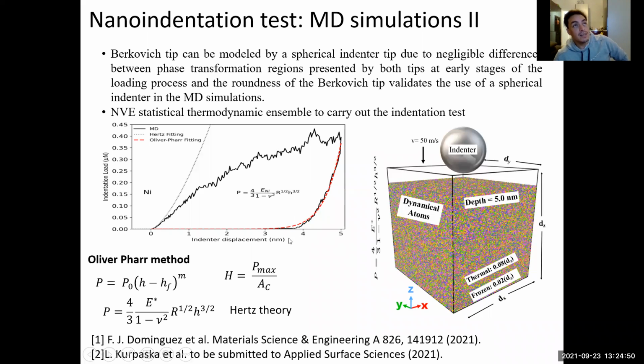This unloading process needs to be elastic and needs to be in really good correspondence with the elastic part at the beginning and at the end of the MD simulation. When we have this, we use the Oliver-Pharr method that is well known in nanoindentation tests. We are using this definition for the load. This hf is the mark that is left by the indenter tip. Then we apply fitting methods to identify this fitting parameter and P0. Then the hardness of the material is computed as the load divided by the contact area.